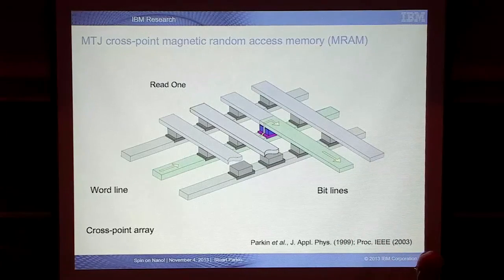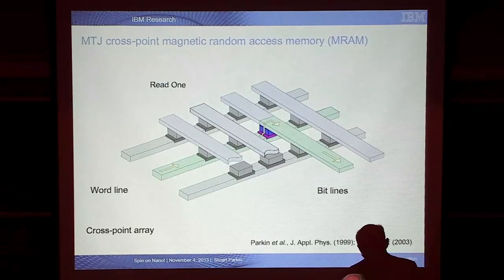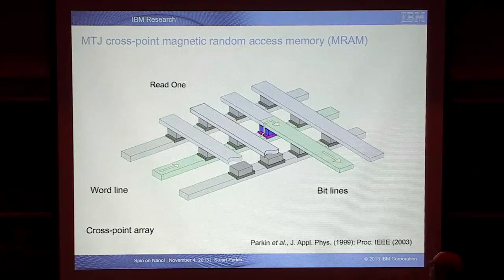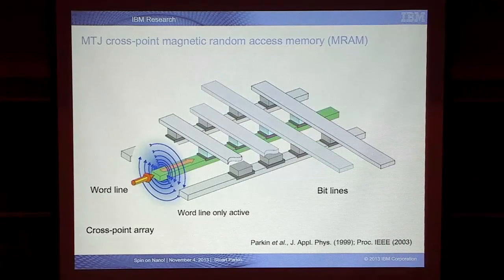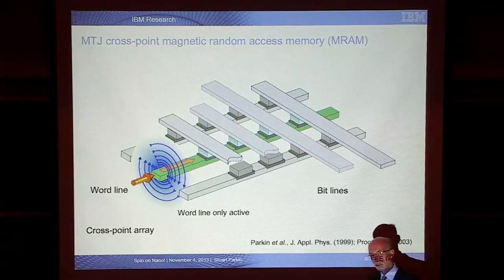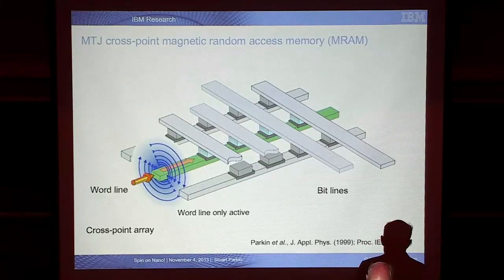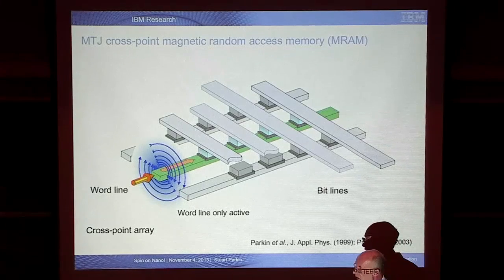So we design the tunnel junction now to essentially have only two states. Now, we proposed this then in, as I said, in 1995, and built the first device in 1999. And in that time, we read the device very trivially by passing currents. We can do that on the nanosecond time scale.